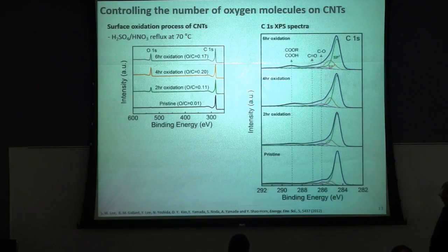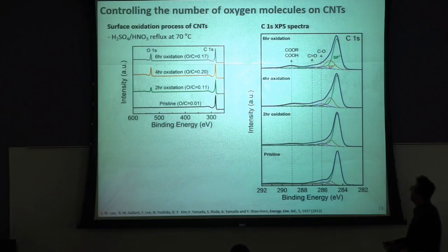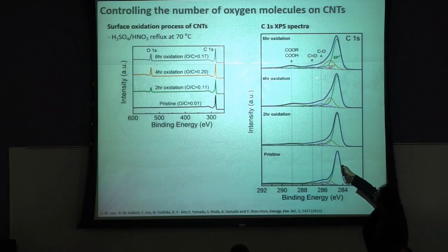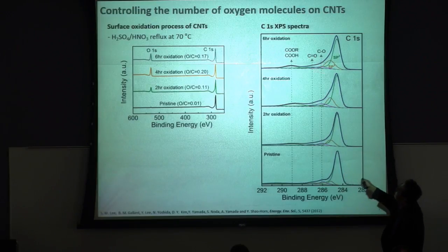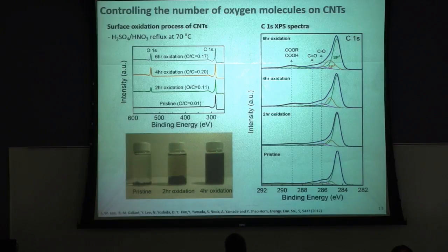Then if we look at the high resolution XPS carbon 1s peak, we can see the gradual incorporation of oxygen functional groups such as carbonyl groups and carboxylic acid groups, and other types of oxygen functional groups. This can also change the dispersion property of the carbon nanotube.